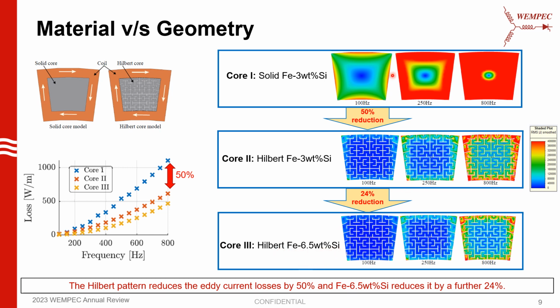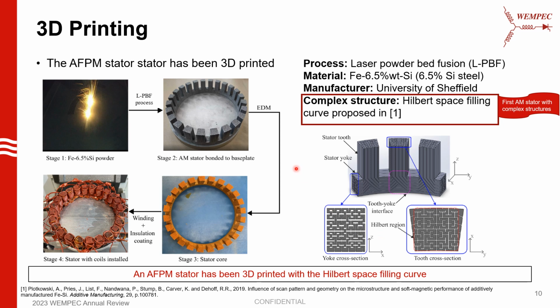The FEA results are shown here, which show that just using the Hilbert core alone reduces the eddy current losses by 50%, and by using 6.5% silicon steel, we get a further 24% reduction in eddy current losses. So motivated by these FEA results, we 3D printed the stator core.